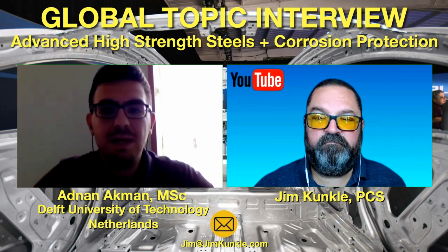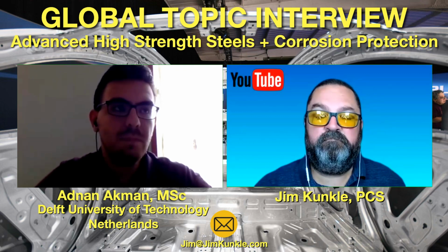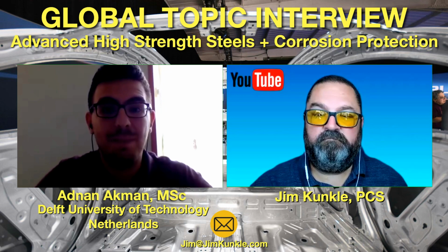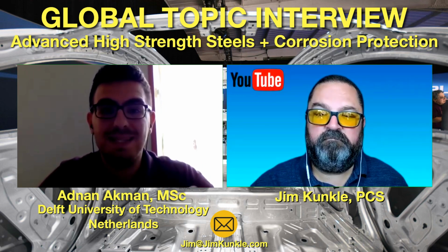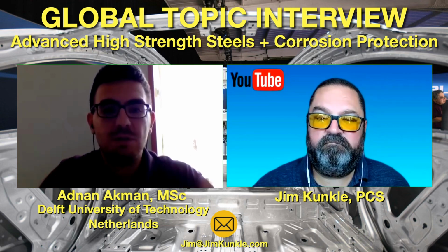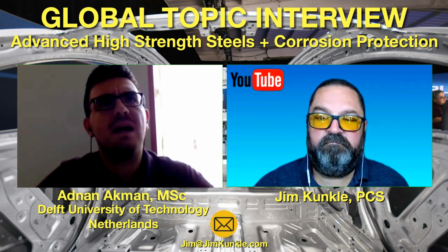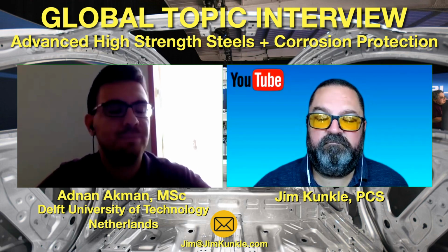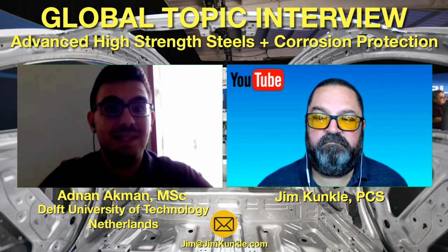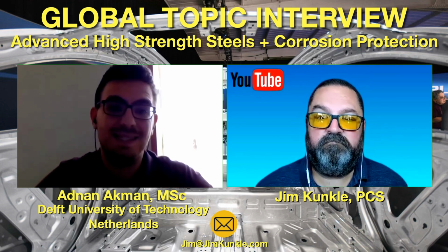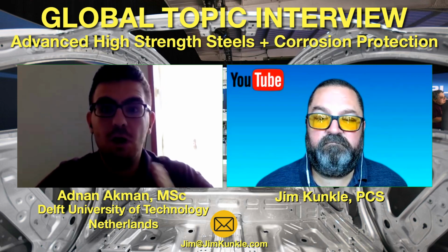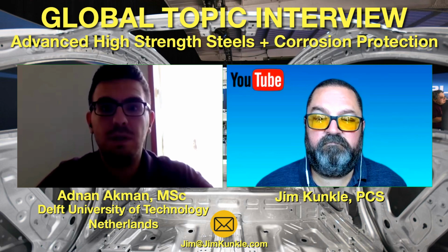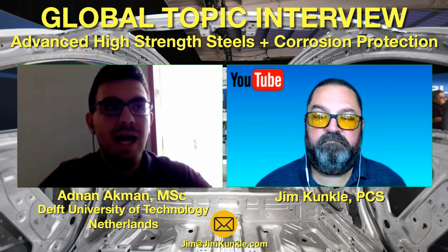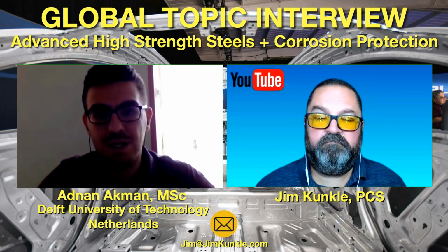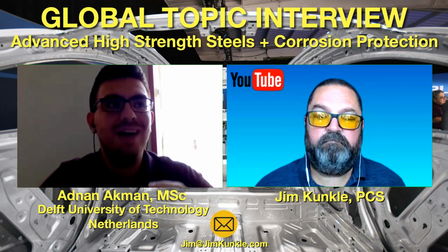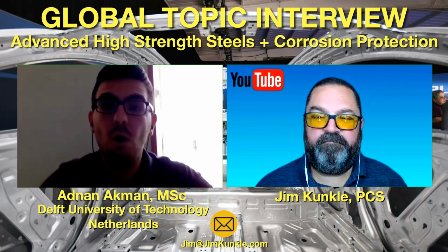So how? Normally, austenite is not a stable phase at room temperature. So how can we stabilize it? Addition of elements. So their chemistry is different. Manganese, for example, in steel, especially in TWIP steel, is used to stabilize austenite at room temperature. TWIP steels contain at least 17% of manganese. Due to this high content of manganese, these TWIP steels are a bit costly, and their forming and welding is a bit of a problem. So in addition to them, third generation advanced high strength steels are quite popular nowadays because engineers are still working on it. The main aim of quenching and partitioning steels from third generation is to achieve high strength and high ductility at the same time, but with lower cost.